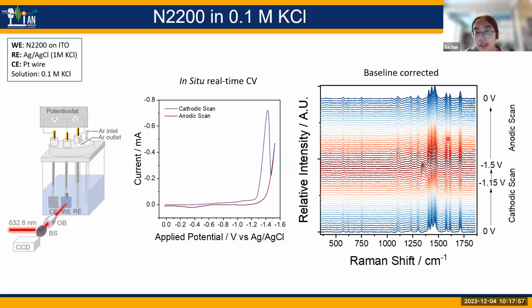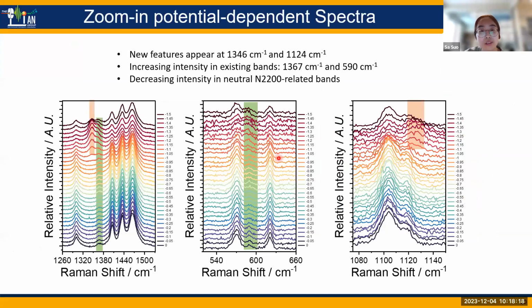And to the right are the stacked Raman spectra during the cathodic scan from 0 to negative 1.5, and then back scan to 0 volts. We can already see some new features occur during the first reduction after negative 1.1 volts. If we take a closer look at the spectra, I just chose three regions which have obvious new features appear.